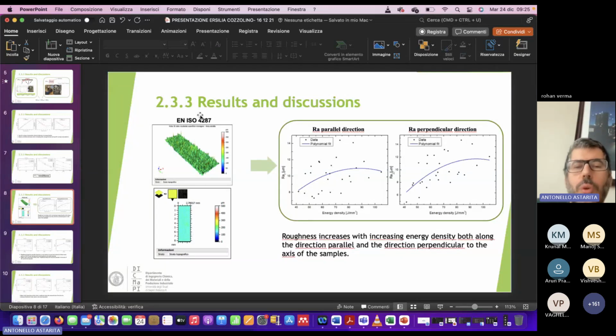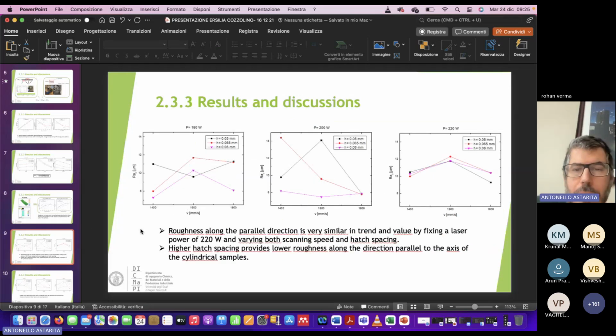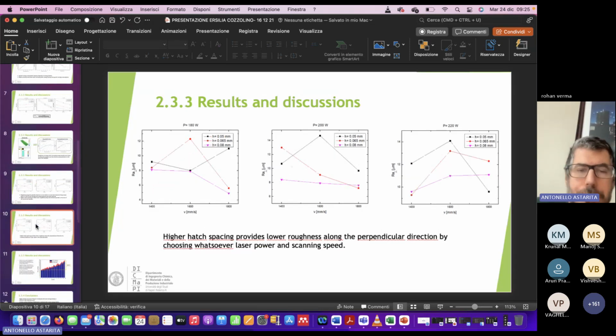Again, we used a Leica DCM 3D confocal scanner to acquire the surfaces and to calculate the surface roughness according to this standard. The results that we obtained were various. We can see that there is no clear relation between the 3D printing process parameters and the roughness parameters, but this is not a big problem because we are going to do machining.